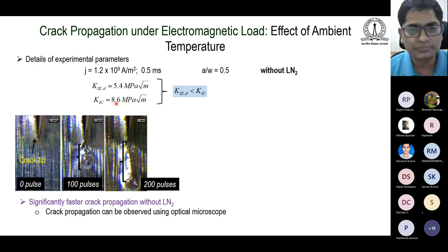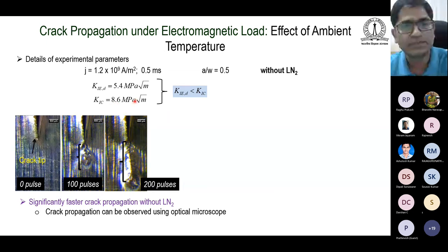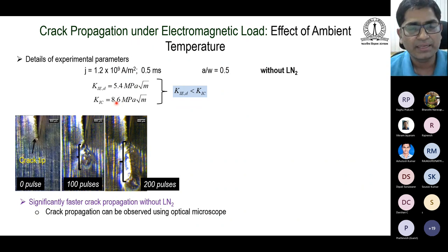And again, we see that the crack grows when essentially we found that the stress intensity factor that we had was actually smaller than this for the crack propagation. But then we think that this is happening because the temperature now is very high. So essentially this K1C, which is okay for the ambient temperature, the room temperature, may not be valid at higher temperatures. And this we can make sense of if we still continue to consider linear elasticity, which again, I think is doubtful. But if you just look at the effect of temperature on the Young's modulus, we will make sense of it. Then we will see that the K1C will decrease as we increase the temperature. But this is again something that we have to fully understand and appreciate.